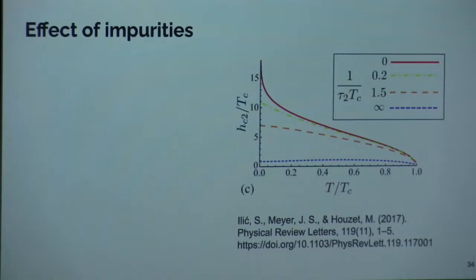So the first thing we tried to do in our complex model was to reproduce this paper here, which is a very nice paper. We checked all the calculations of this paper. It's very well done, and we think it's correct. So we used this as a test, but we did not see a suppression of the critical field numerically. No suppression whatsoever. So this was very, very puzzling at the beginning, but we later understood where the robustness comes from.